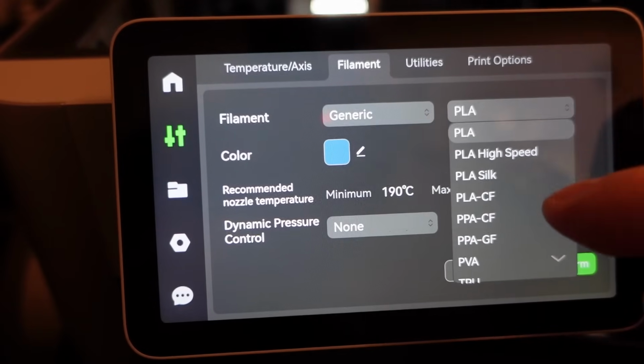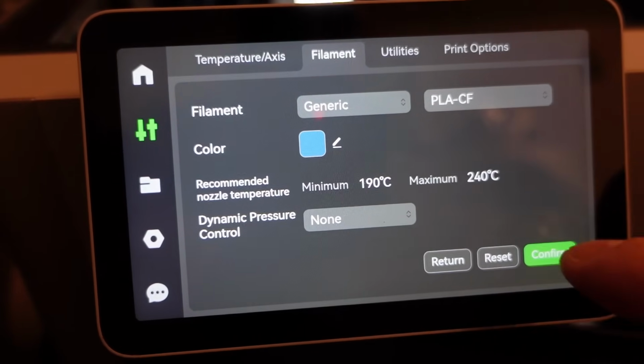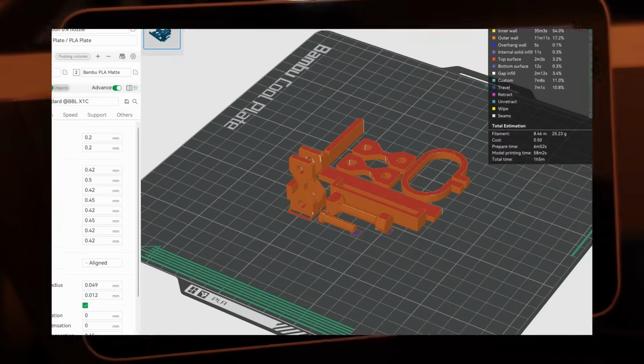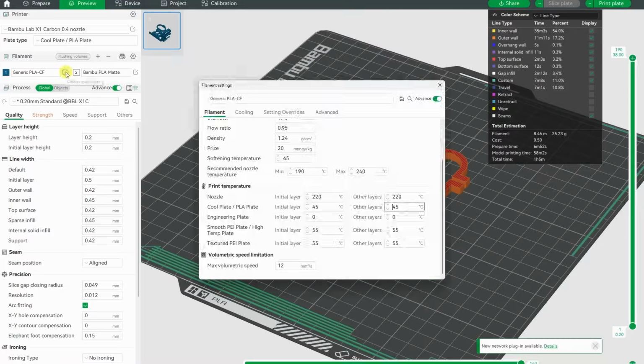This is the X1 Carbon, and I'm setting the generic PLA-CF material here. I also checked the properties in Bambu Studio: the default maximum flow rate is 12 cubic millimeters per second, while the Bambu version of this material is 15 by default. Here you can see some real-time footage of the printing, if you are not familiar with the speed of this printer.